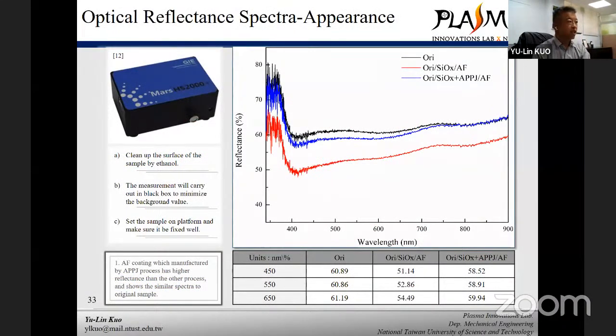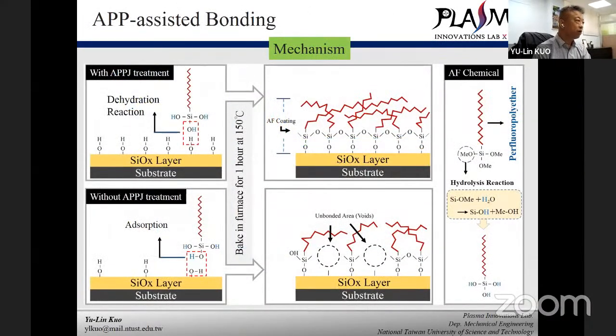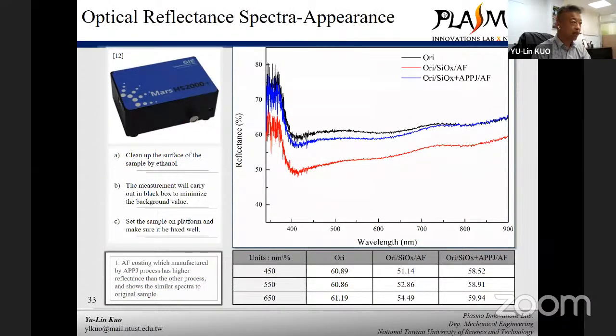So if we go back to this, the optical reflectance spectrum for the appearance: the black one is the original one, the blue one is with the APPJ treatment, and the red one is without the plasma treatment. So that's why we propose the mechanism that without the APPJ treatment, you should obtain some voids in the coatings, which means that your reflectance for the appearance will be sacrificed. However, using the plasma treatment on the silicon oxide, your anti-fingerprint will be successfully and uniformly coated on the surface, even though we still have some visible light sacrifice in this region. But compared with the one without the plasma treatment, we can see this is quite successful.